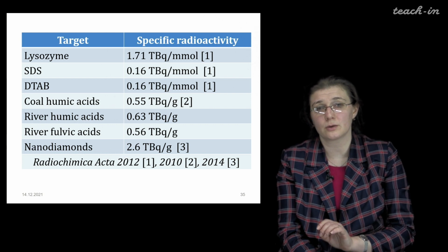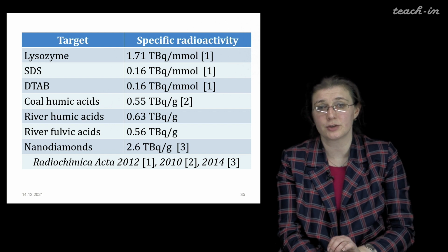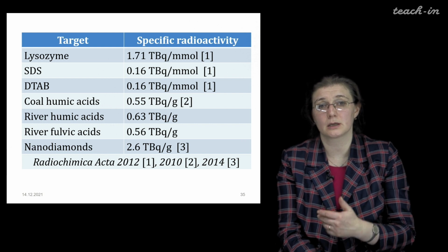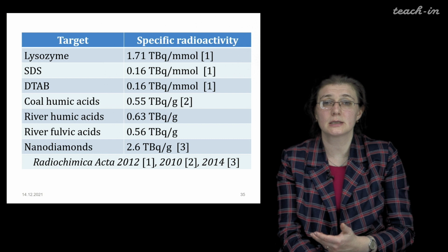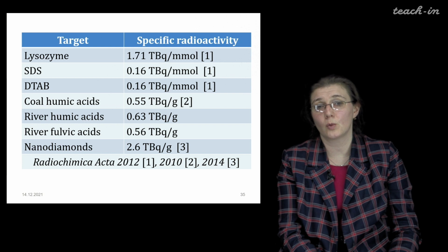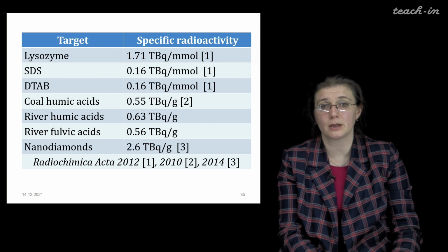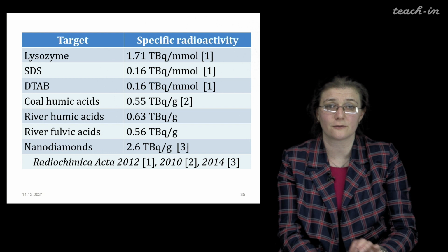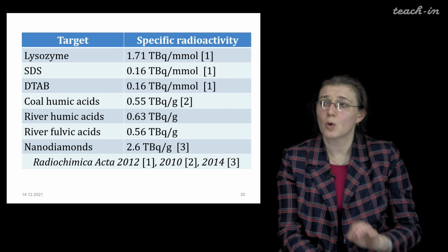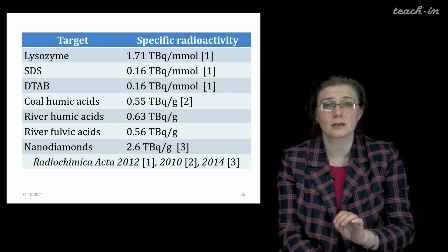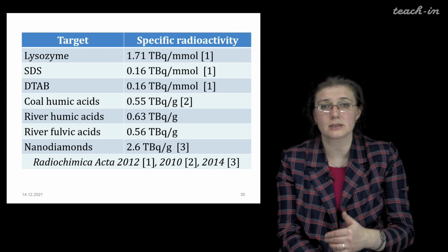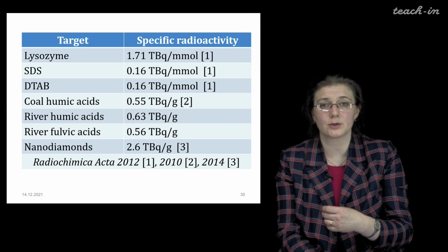If the material contains hydrogen, even in trace amounts, like carbon nanotubes, we can subject it to radiolabeling by means of the tritium thermal activation method and obtain a radioactive product with the same physical and chemical characteristics as the initial material, but containing a radioactive label.